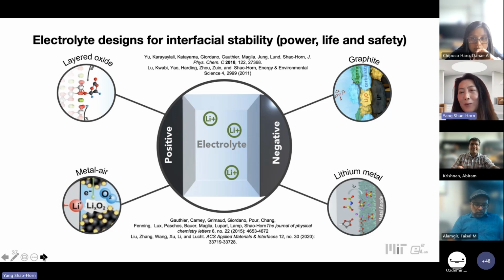For example, we have a known electrolyte that can stabilize graphite. In lithium-ion batteries, for the past decade we have been dealing with the challenge of gradually increasing nickel to increase the energy density of lithium-ion. But this is typically associated with degradation of cycle life and also safety. This has to do with the instability of carbonate electrolytes towards a high-nickel positive electrode. And today, we don't have a viable, stable electrolyte against metal, nor against the oxygen electrode.